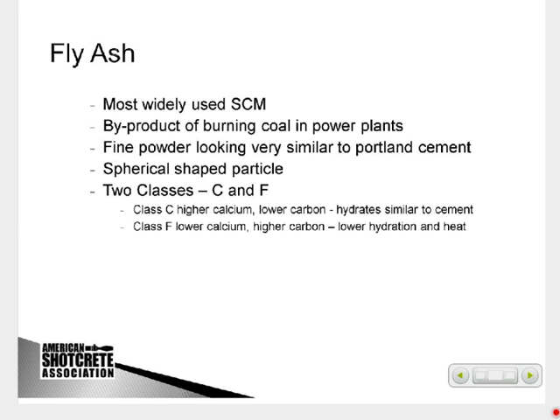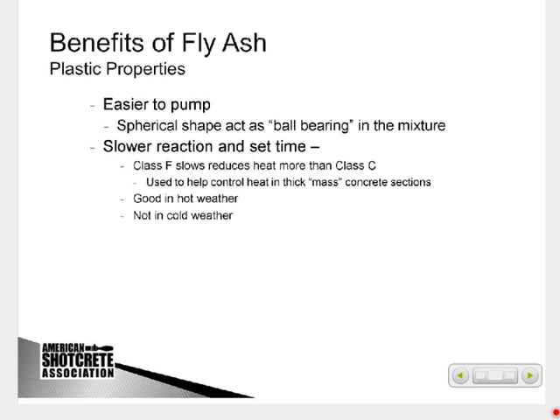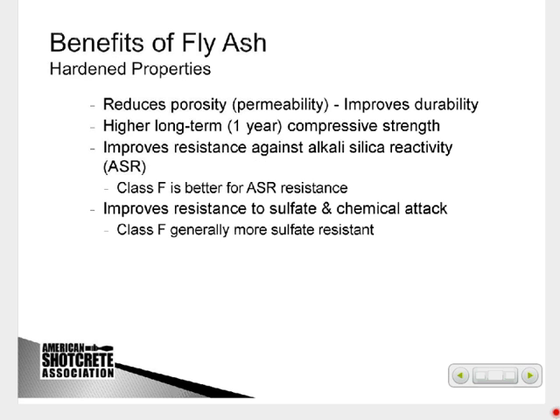In the summer, it will slow down your set. In the winter, you may not want to use fly ash in shotcrete, especially if you're overhead or in vertical surfaces where you want to have that set up faster. It does make it easier to pump if you're in wet mix because the fly ash acts as little ball bearings, as small round particles. There's a couple different classes. So once again, it's good in hot weather, but maybe not so good in cold weather.